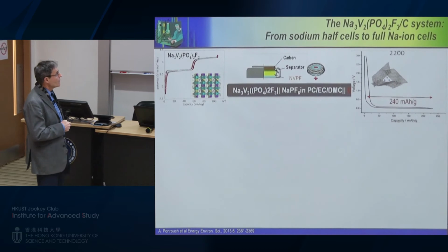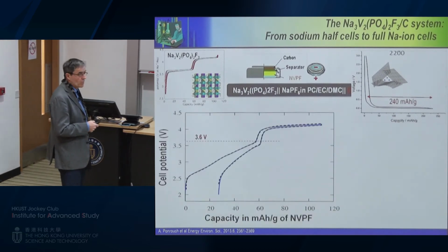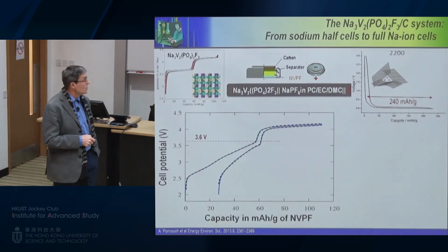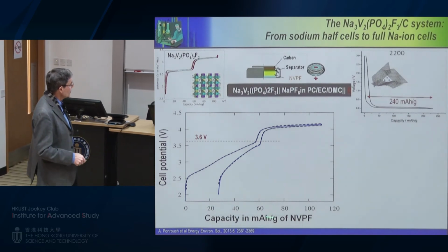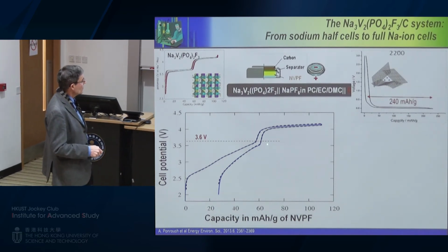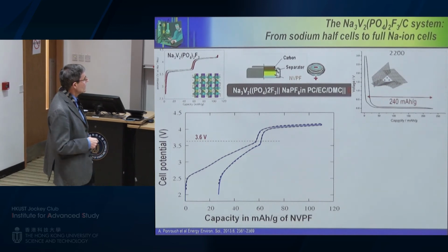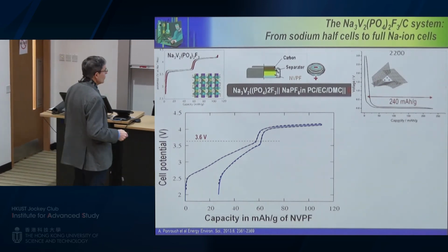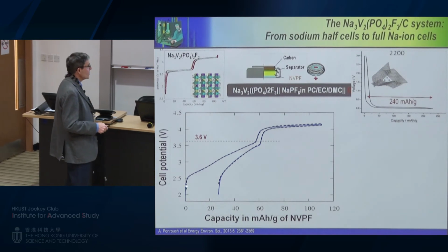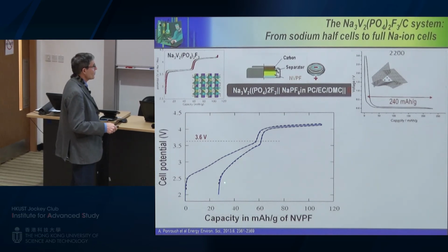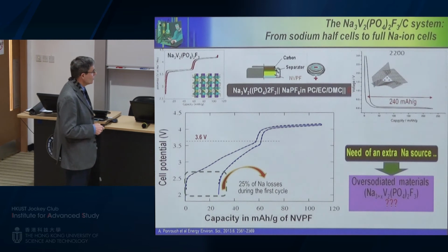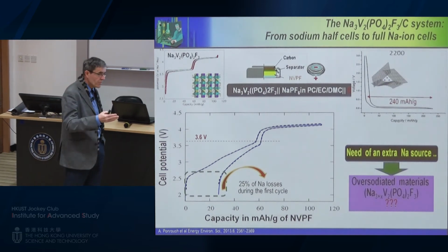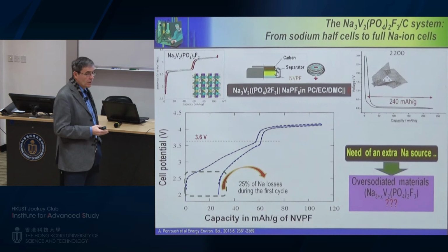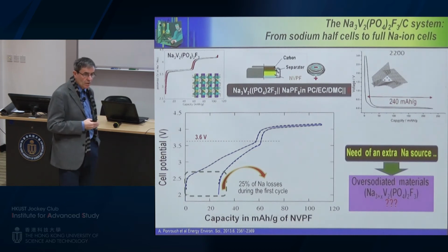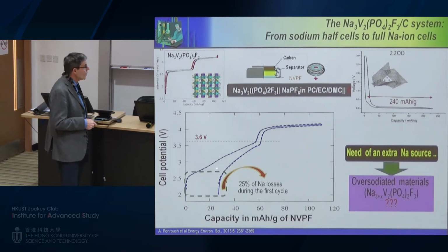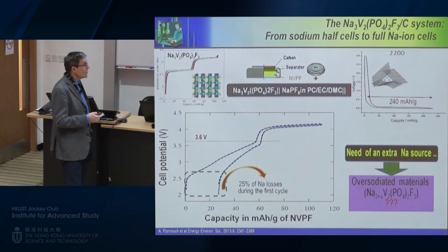And when you assemble this cell as a coin cell, this is more or less a typical voltage-composition curve that you obtain: cell potential as a function of capacity, average voltage of 3.6 volts. But when you make this kind of coin cell, you note that you have a huge irreversible capacity between the first charge and the first discharge. Which means through the process, you are losing about 25% of sodium in the system. So automatically, you could not really commercialize these materials. You need to find a solution.